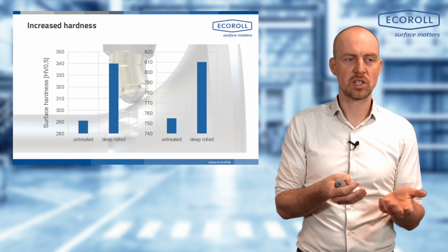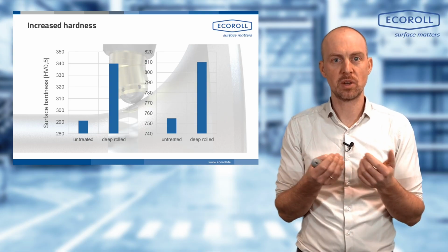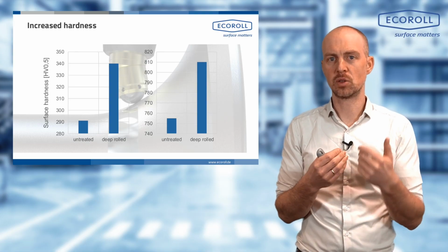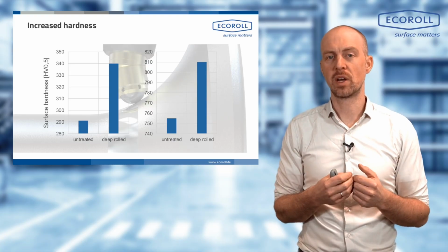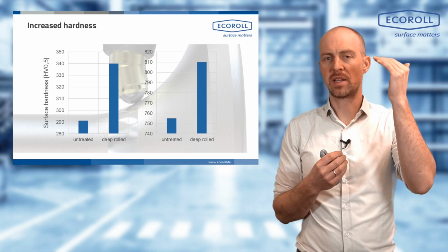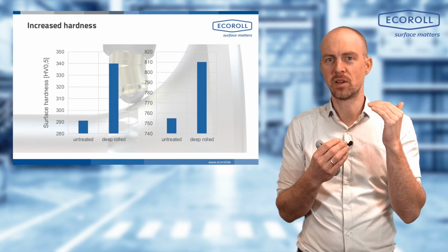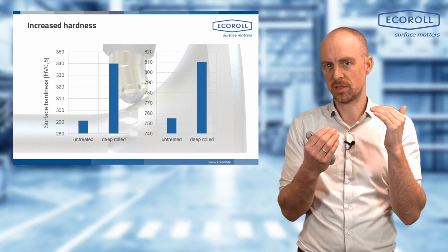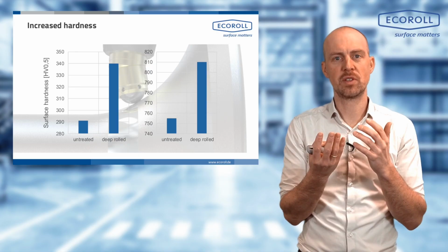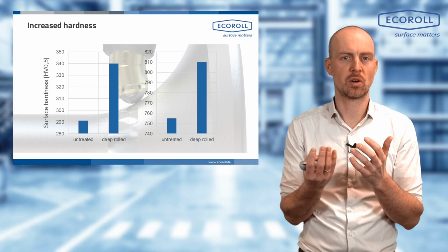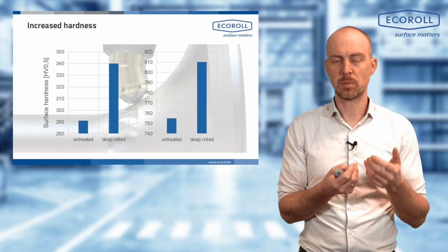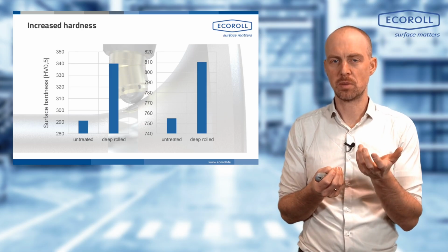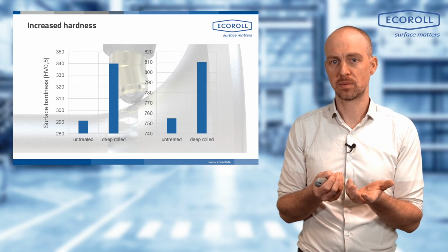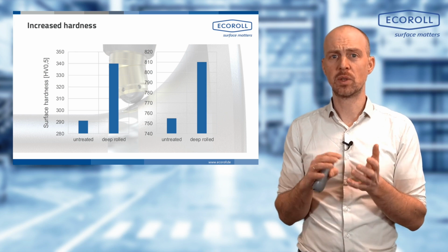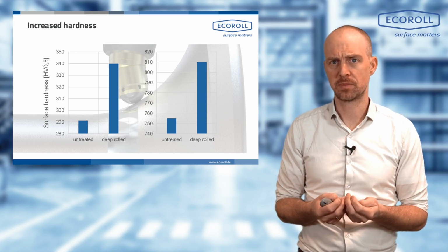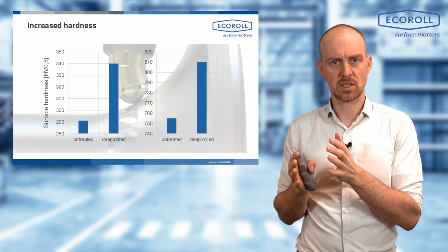If I have a penetration depth of 1, 2, or 3 millimeters with induction hardening to a certain hardness value that's also relatively high, I can control that by simply adjusting my heating depth through the induction heating accordingly. And then, due to the physical effect, I simply get a transformation of the microstructure. With mechanical stress, the mechanical tension must act down to this depth. And that becomes difficult again with such high hardness penetration depths. So there are limits where it just doesn't work.